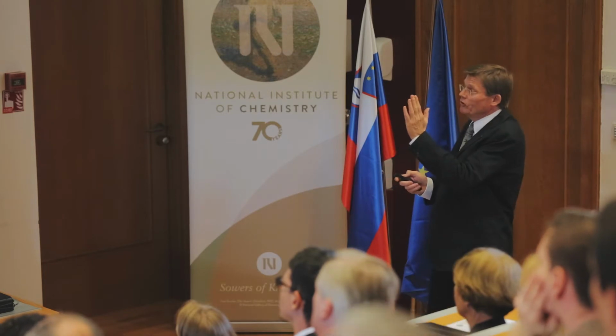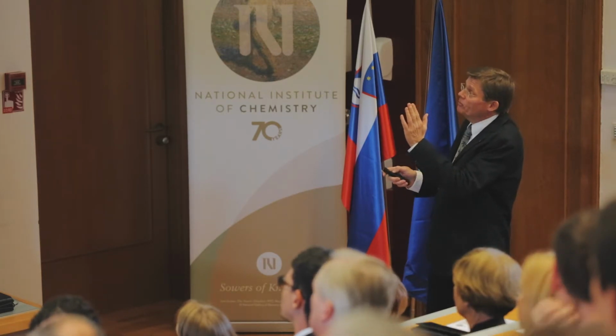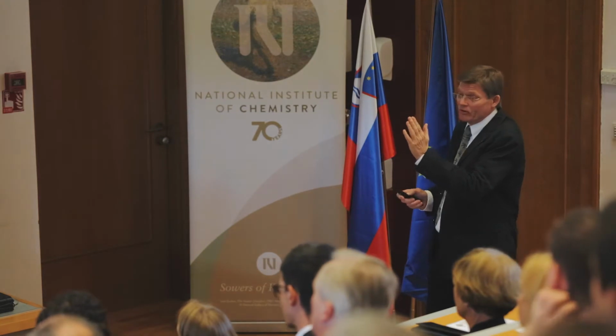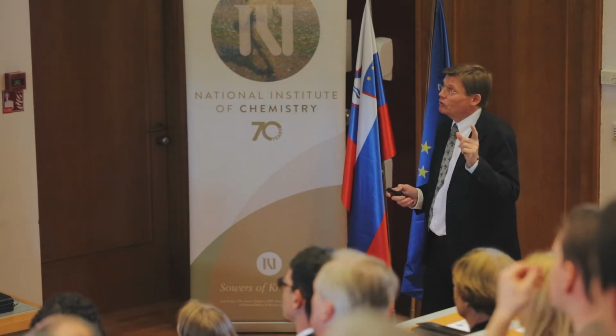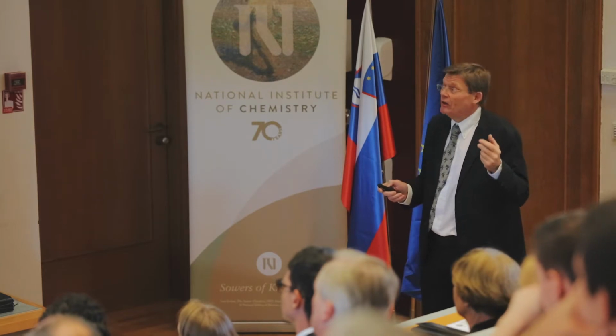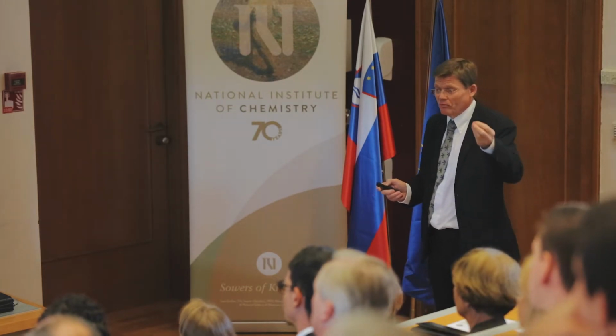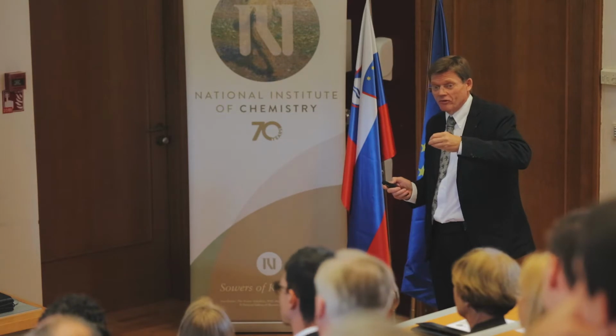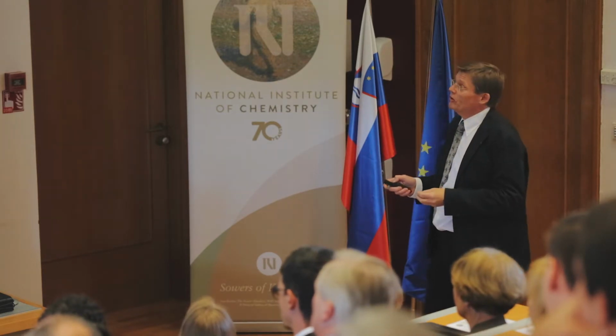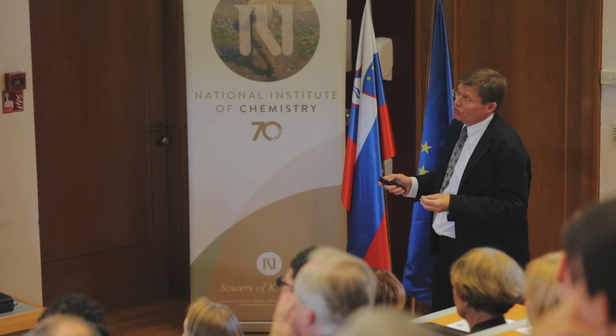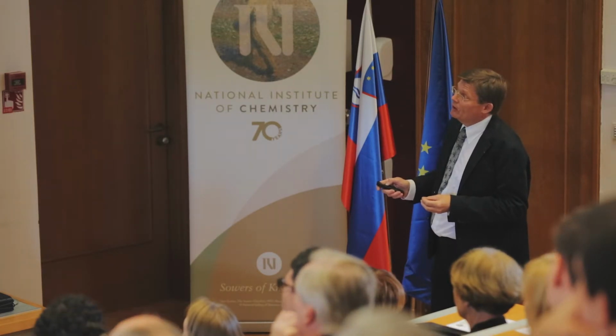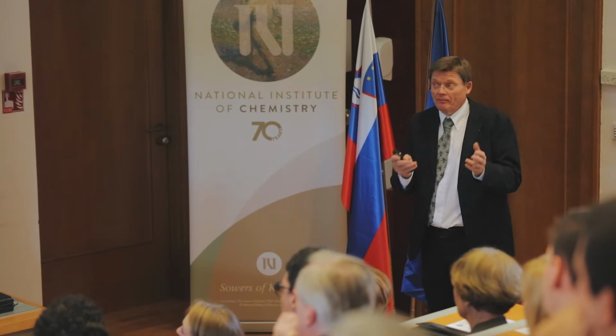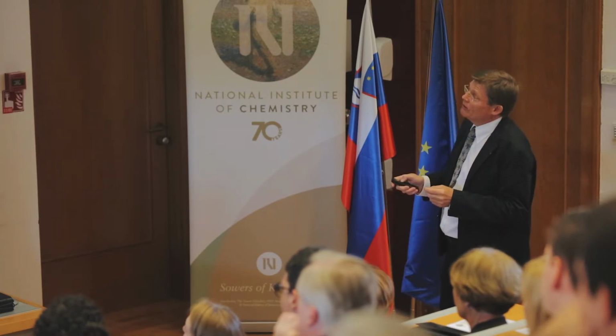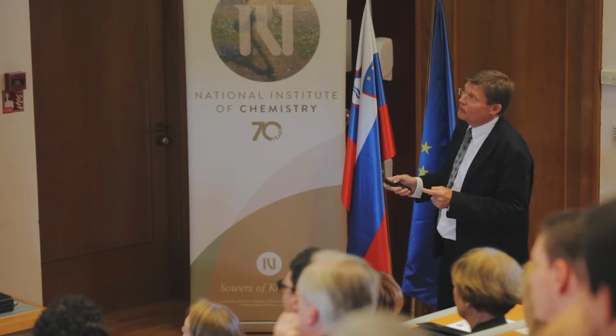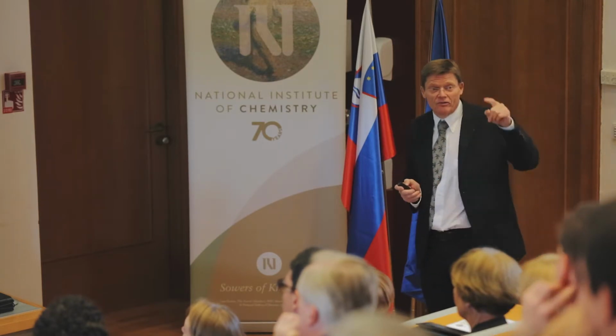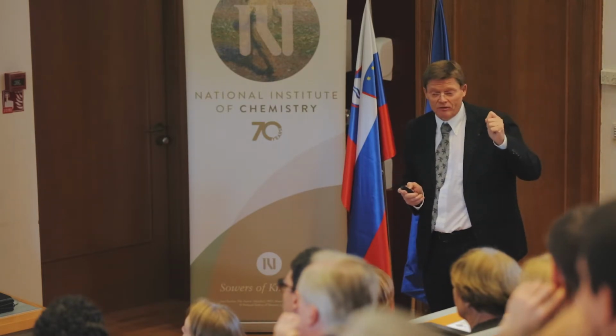And if this boundary is positively charged, all the positive carriers have to be, for electrostatic reasons, depleted. There are two carriers which are positively charged. These are the oxygen vacancies, missing O2-, like a positively charged missing situation, and we have a missing electron, which is a hole. Both are depleted. But it's important to see that the vacancies are much more strongly depleted than the holes because of the double charge, and this goes exponentially. It's really a huge difference.